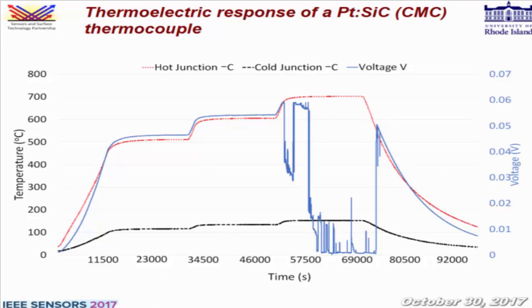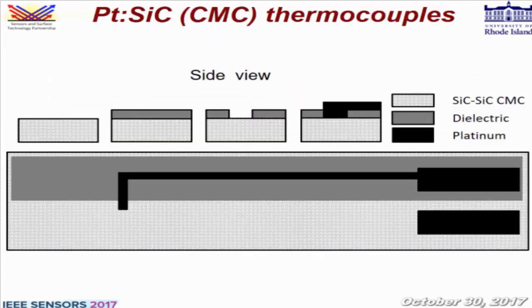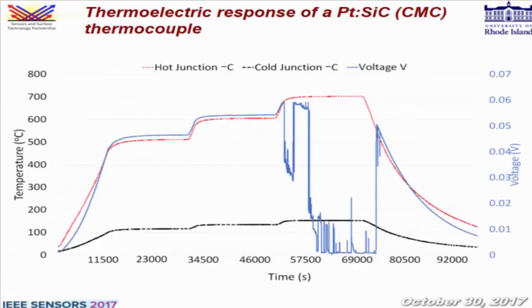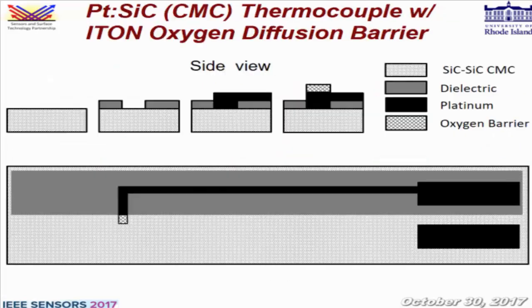The reason it's failing here is that oxygen is now diffusing through the platinum and reacting with the silicon carbide, forming a layer of silicon oxide which lives between the platinum and the silicon carbide. So we had to figure out a way to prevent the oxygen from diffusing, and we came up with this approach. The processing steps are all the same, except that now we sputter coat a layer of indium tin oxynitride, and it has a great ability at preventing oxygen from diffusing through it.